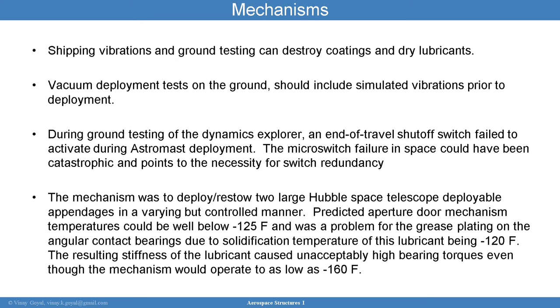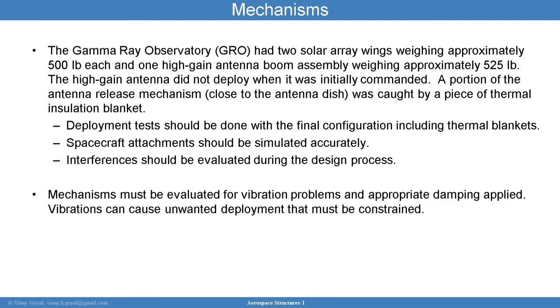Another example is the mechanism that was to deploy two large Hubble Space Telescope deployable appendages in a varying but controlled manner. The predicted aperture door mechanism temperatures could be well below negative 125, and was a problem for the grease plating on the angular contact bearing due to the solidification temperature of this lubricant being negative 120F. So the resulting stiffness of the lubricant caused unacceptably high bearing torque, even though the mechanism will operate as low as negative 160.